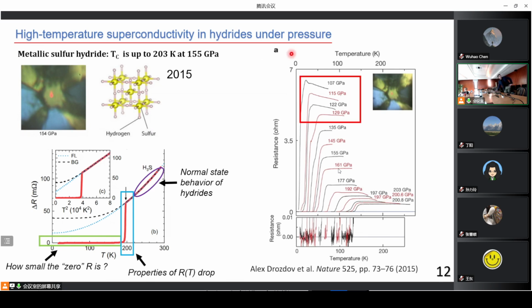But the most interesting case is low pressures. After they decompressed the compound and decreased the pressure in the cell, they found that there is a reversed sign of the temperature coefficient of resistance at low pressures. We can see that first this derivative of resistance becomes zero, and after that changes its sign. And now the behavior of H3S is not metal-like, but semiconductor-like. It's very unusual for metals, and it's very unexpected. The dependence is linear, and it changes gradually. There are no sudden drops, sudden changes, or fluctuations, so it probably belongs to the sample.